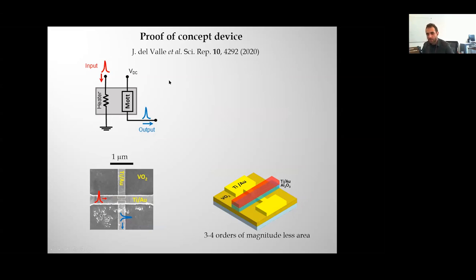We actually fabricated a proof of concept device that you have here. This is an SEM image of the device, and this is a schematic representation. This device consists of two titanium-gold electrodes at the bottom. You can see them here. There is a gap in between them, a VO2 gap, which would be this element. And then on top of it, there is this stripe, this contact that would act as a heater. You can see it here.